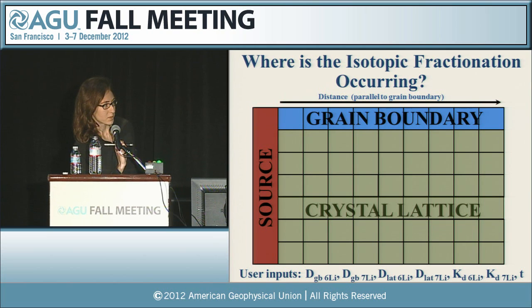So the user inputs are 2 diffusivities for lithium-6, one in the grain boundary, one in the crystal lattice. The same thing for lithium-7, and a partitioning value for both isotopes and time. So the good thing about this model is you can control where the fractionation is occurring. If, for example, you would only like isotopic fractionation to occur in your grain boundary, then you would set the diffusivities of lithium-6 and lithium-7 in your crystal lattice to be equal, whereas in the grain boundary they would be different.